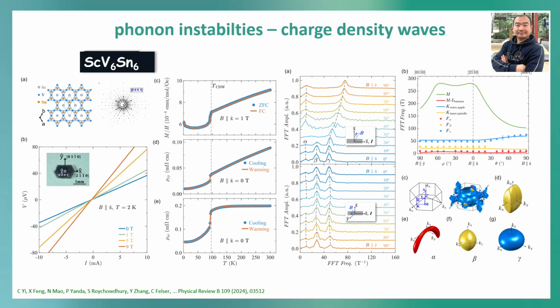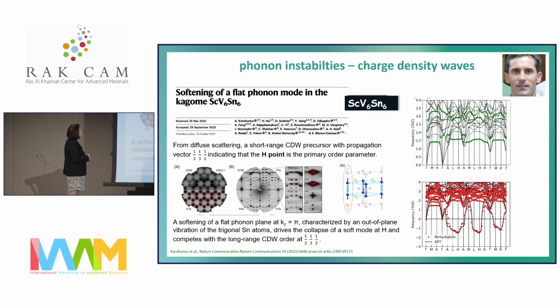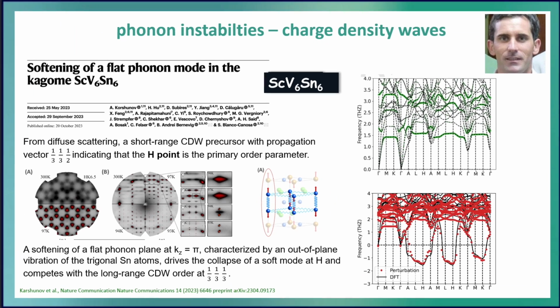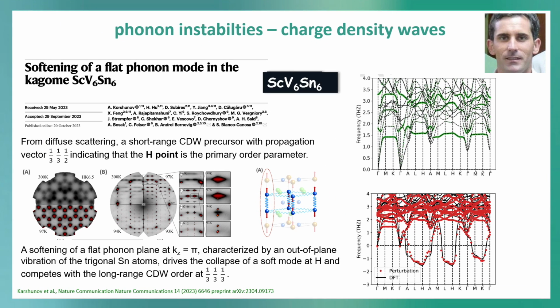This compound shows a Van Hove singularity, and related to the Van Hove singularity and the flat band, they show phonon softening, they show charge density wave. So this is also predictable by theory. Here we calculate the phonon frequency, and if you find values below 0, you already see it, and if you look at the symmetry of the phonon, you can already predict where the structural distortion is and where the charge density wave appears. So here you see, for example, we find the charge density wave between the layers, so between the tin atoms, and this was then verified by experiment.